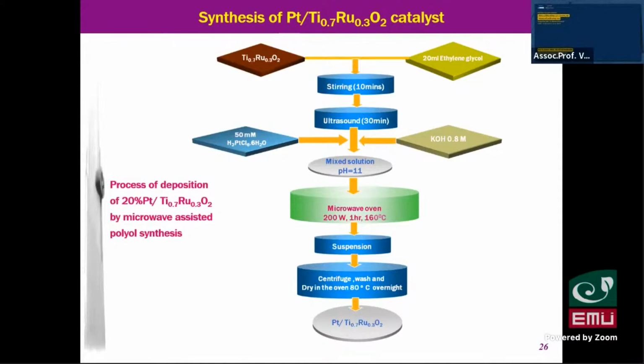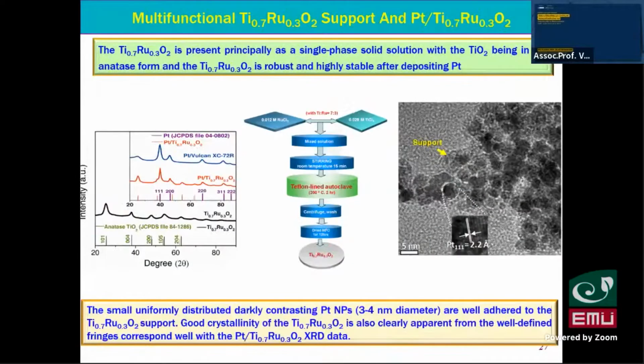The scheme here is very simple; the process is not complicated, just one step at low temperature. We found a very nice TEM image showing the platinum, the black particles, dispersed on the titanium ruthenate oxide support. This is the XRD showing the structure of our catalyst.